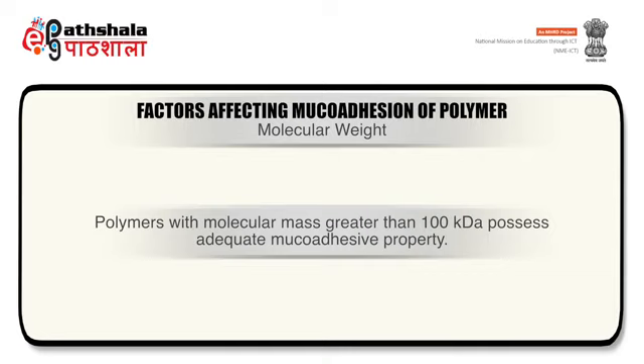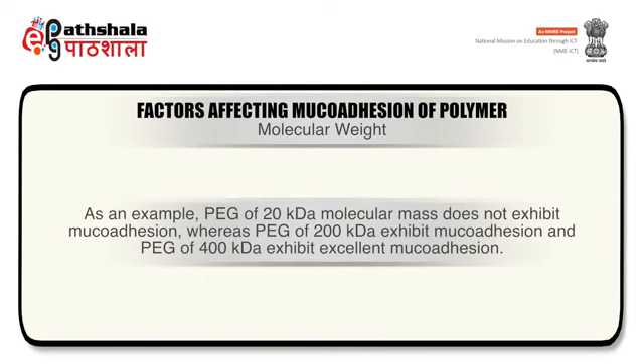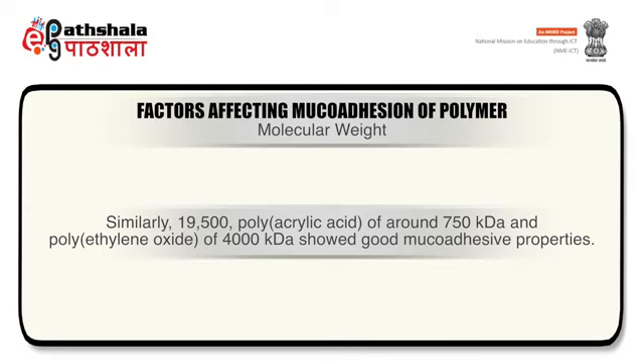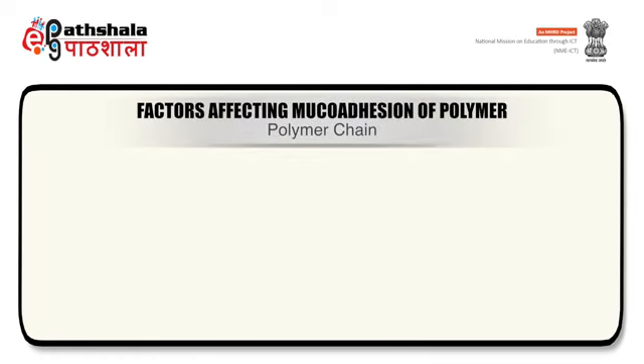Polymers with molecular weight greater than 100 kilodalton possess adequate mucoadhesive property. As for example, PEG of 20 kilodalton molecular weight does not exhibit mucoadhesion, whereas PEG of 200 kilodalton exhibits mucoadhesion and PEG of 400 kilodalton exhibits excellent mucoadhesive properties. Similarly, polyacrylic acid of around 750 kilodaltons, polyethylene oxides of around 4000 kilodaltons and dextrans of around 19,500 kilodaltons showed good mucoadhesive properties. The second parameter is polymer chain.